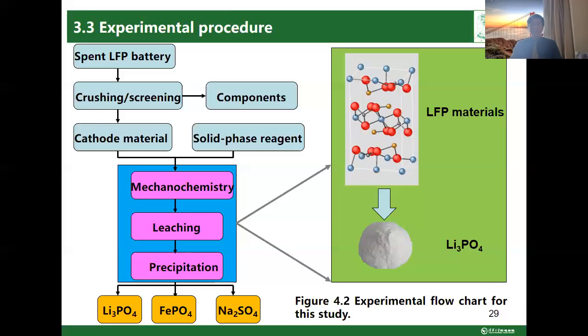The zirconia ball mill jar was sealed and placed in a high energy planetary ball mill for reaction at different time intervals and different rotary speeds. After the reaction, the sample was directly dissolved in deionized water and filtered through a 0.2 μm filter. And the metal contents of the lithium and iron ions were measured in an inductively coupled plasma optical emission spectrometer. And the leaching percentage of lithium and iron was calculated based on the test result.